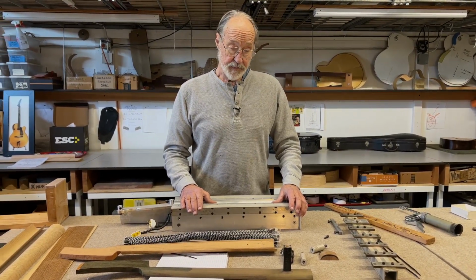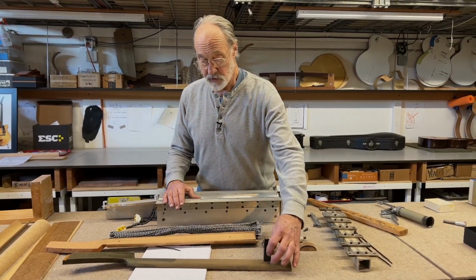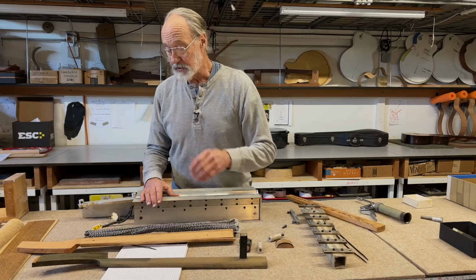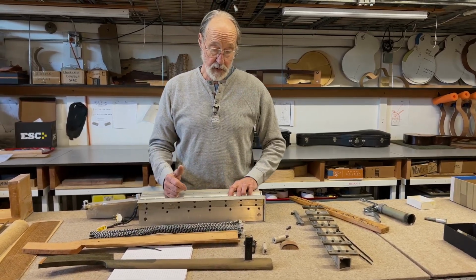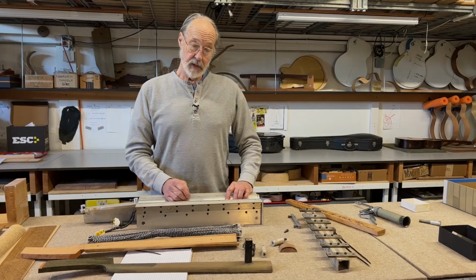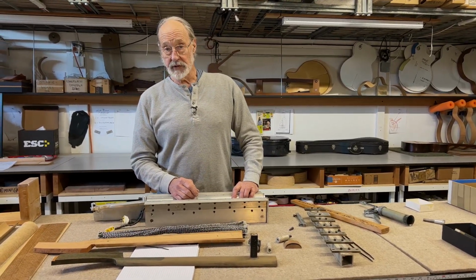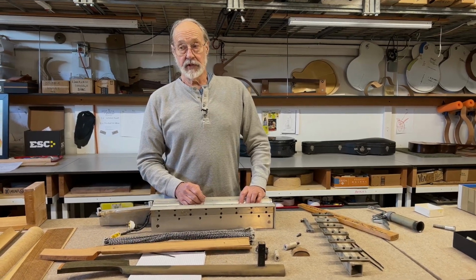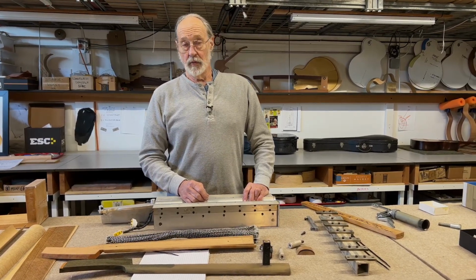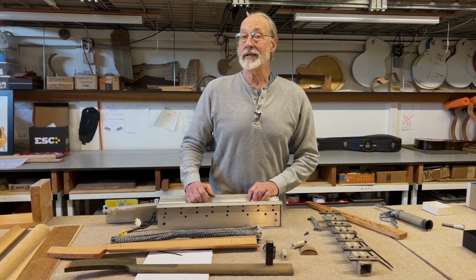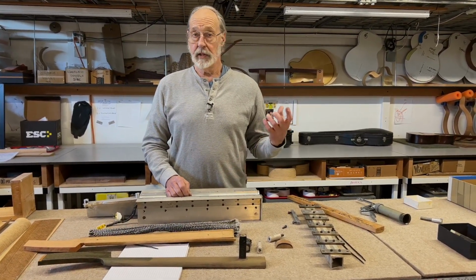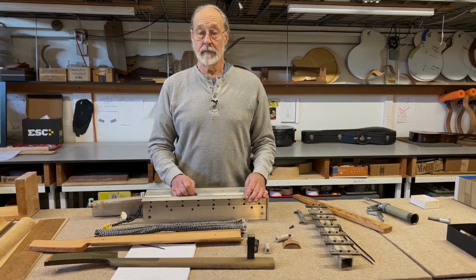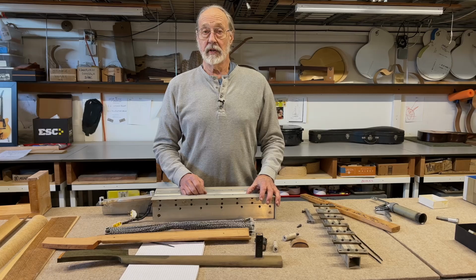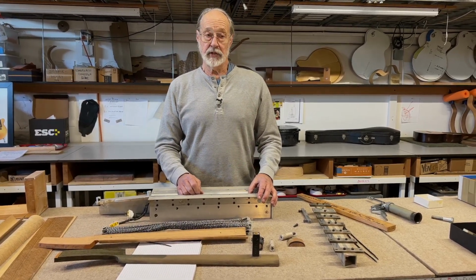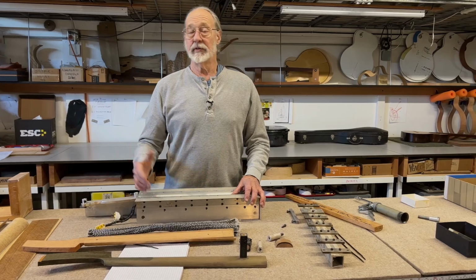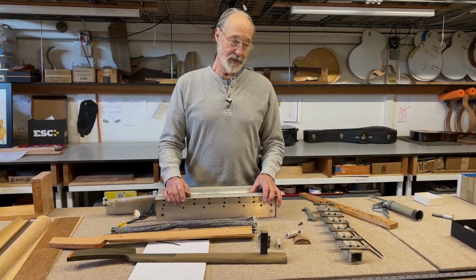I'm very happy with it. The system works great. You get a perfect neck joint. You can always depend on the neck joint's relationship to the rest of the neck. It comes out automatically from being molded. And finally, because the resonant frequency is high and the stiffness is so good, it does not support a lot of unwanted resonances, which can lead to either hot spots, in other words, unusually prominent or loud notes, or dead spots, notes that are a product of conflict between the note you're trying to play and the vibratory behavior of the neck. I'm very happy with this method.